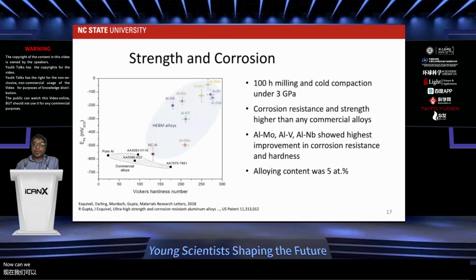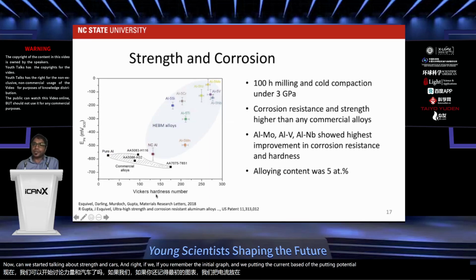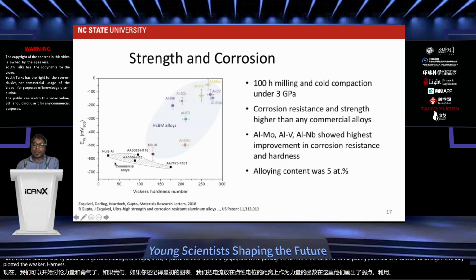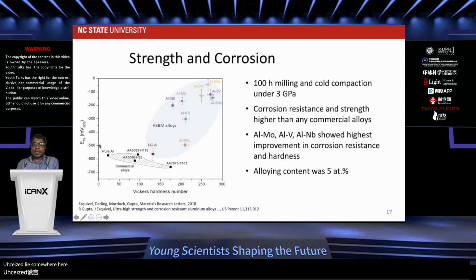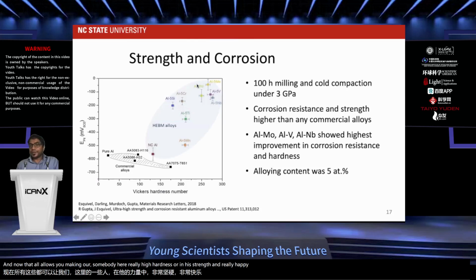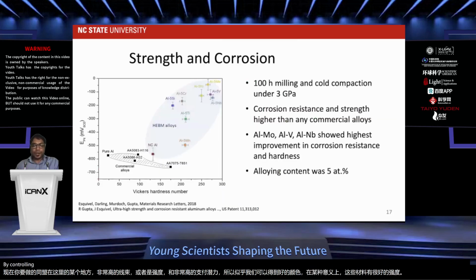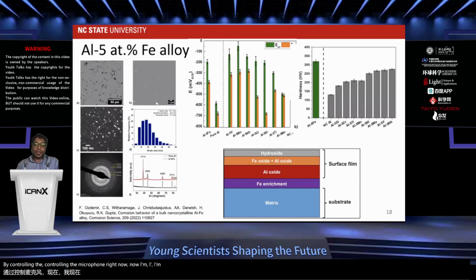Now, we started talking about strength and corrosion, right? If you remember the initial graph where we plotted the corrosion resistance, the pitting potential, as a function of strength, here we plotted the Vickers hardness. Commercial alloys lie somewhere in this region here. We see that pure aluminum has good corrosion resistance, but very low hardness, right? 7075-T651 has the lowest pitting potential, highest hardness. And now the alloys we're making are somewhere here, really high hardness or strength and really high pitting potential. So it seems like we can get good corrosion resistance and good strength in these materials by controlling the microstructure, right?